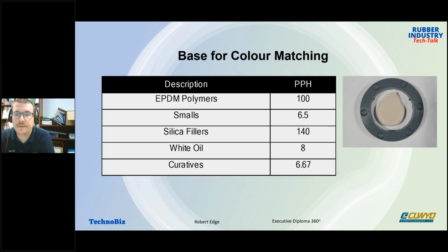So here's a base for color matching, just a simple EPDM formulation with your polymer, your additives, fillers, curatives, and oil. So the first thing we would do is cure this compound and test the rheology as well. Then we would look at what the hardness of that compound is, as there's no reason to carry on trying to color match this compound if you're not in the specification to begin with. As you can see, this compound isn't pure white to start from at the base, and it's not too dark as well, to make it more difficult, as we discussed.